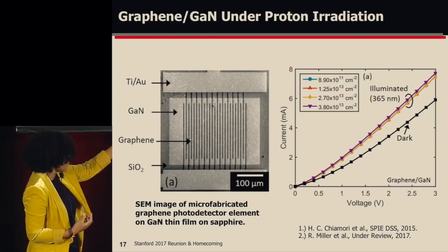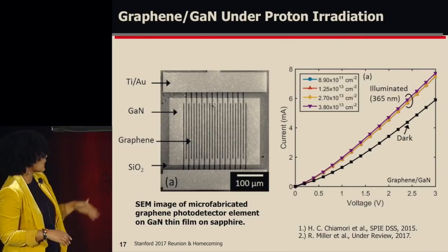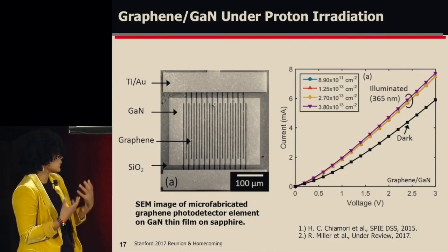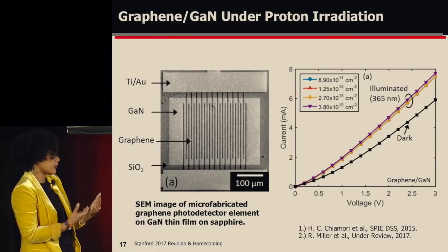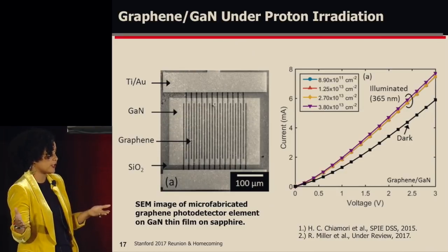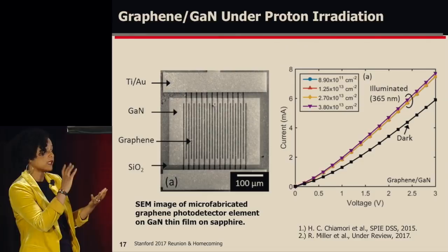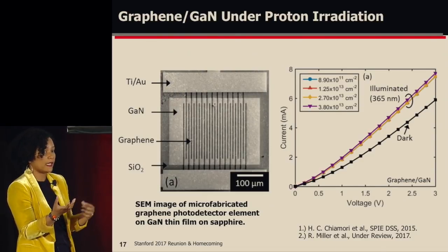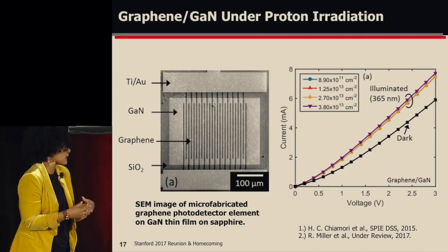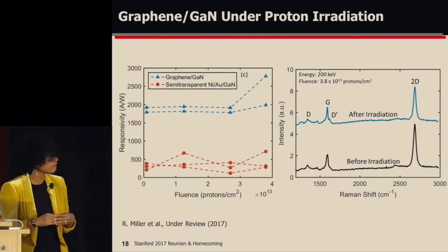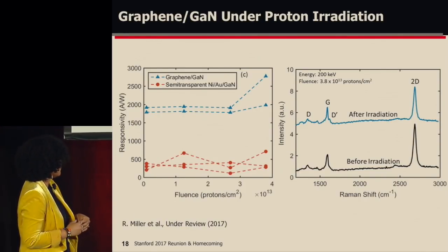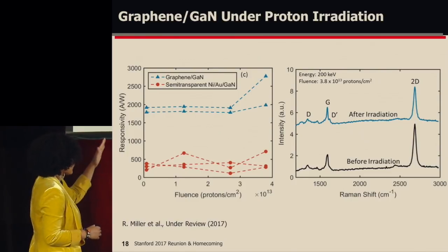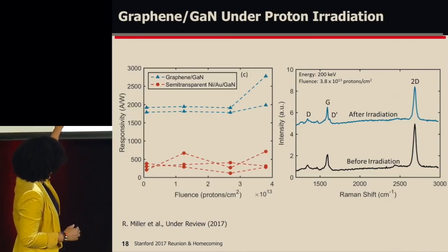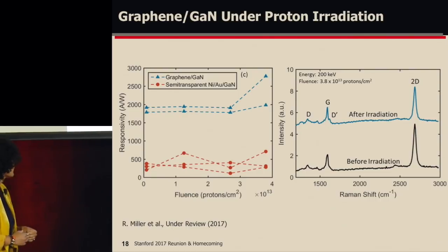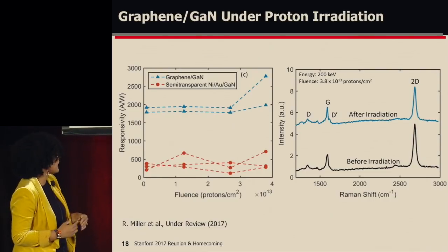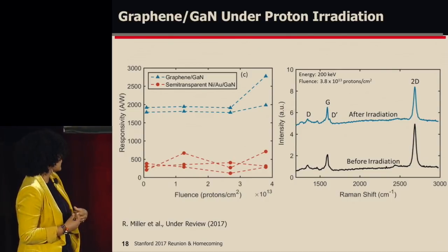So the black curve is the IV response under dark conditions, and then the colored curves are the IV response, or current voltage response, under ultraviolet stimulation. And we observe the evolution of the IV characteristics upon irradiation of protons. And we can see that those IV curves start to collapse. So the radiation is actually not degrading our device, and this is an unshielded electronic device that's surviving high proton irradiation. So we've studied the responsivity of our device over increasing fluence, so over protons per area. We can see as that increases up to around 2.5 times 10 to the 13 protons per centimeter squared, it's very, very stable in comparison to your traditional metal electrodes.